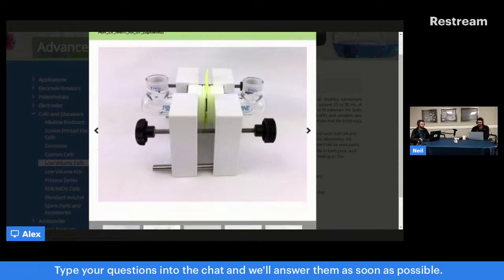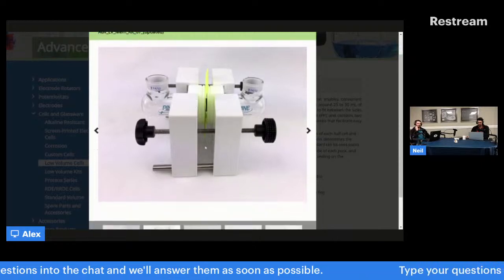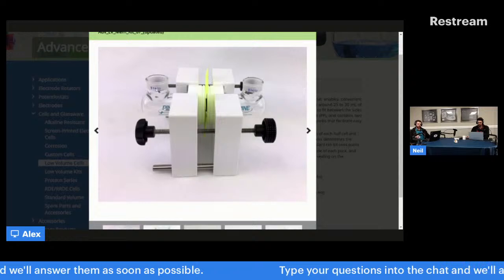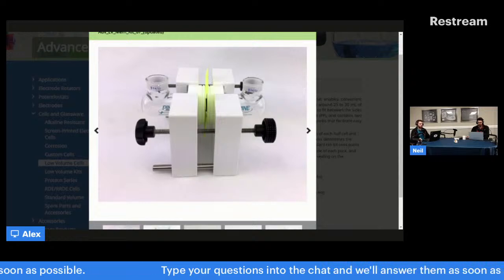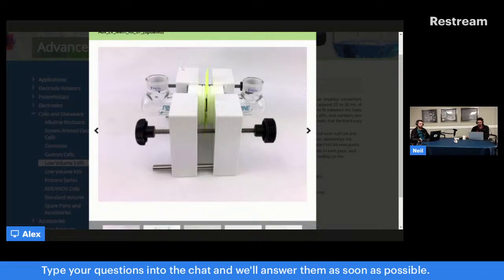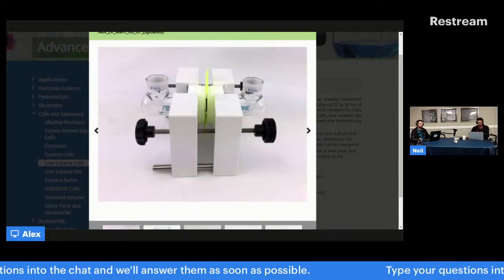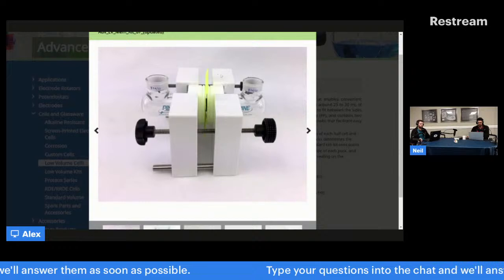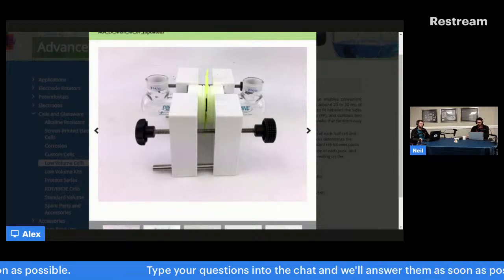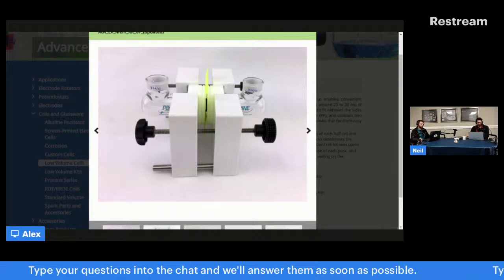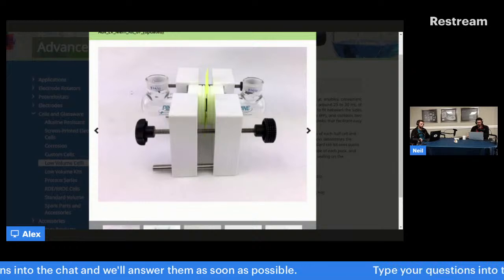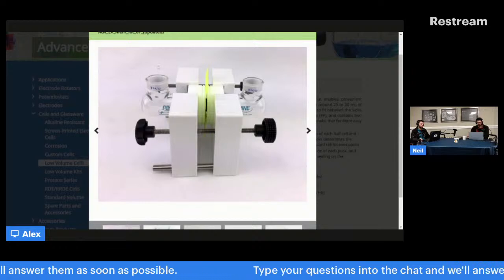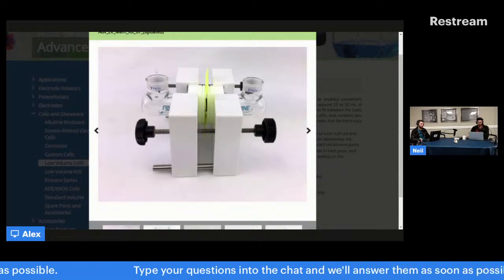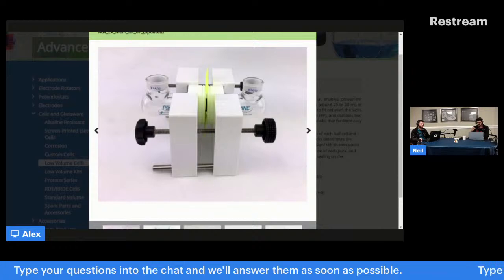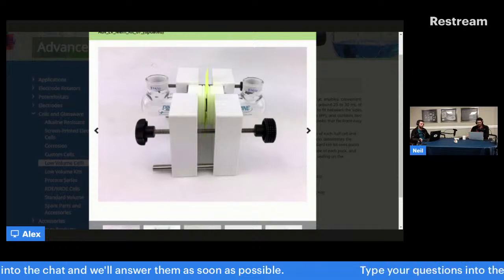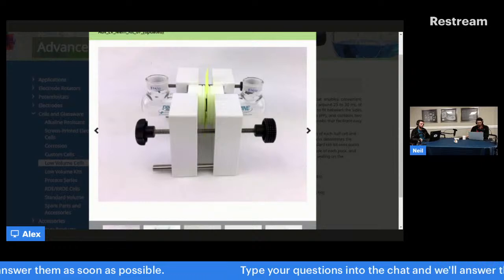This is one of our advanced membrane cells. So there's two cells. Your membrane would be here, and then you would put electrodes on either side. In some ionic conductivity experiments, they might just put two platinum electrodes. You want something that's conductive on both sides, or at least very conductive on both sides. And then you would do impedance to get the resistance. And then 1 over the resistance would give you the conductivity. And impedance actually gives you a much better description because it's a frequency-based resistance, or a frequency-based impedance.